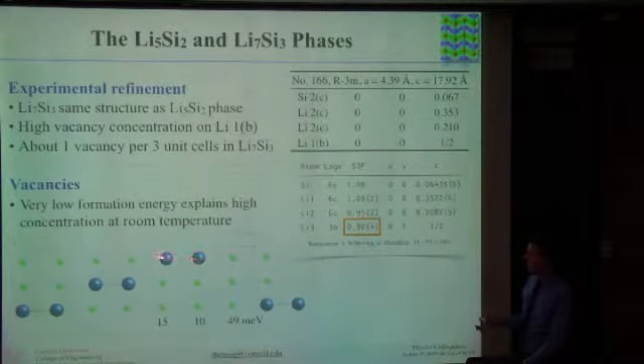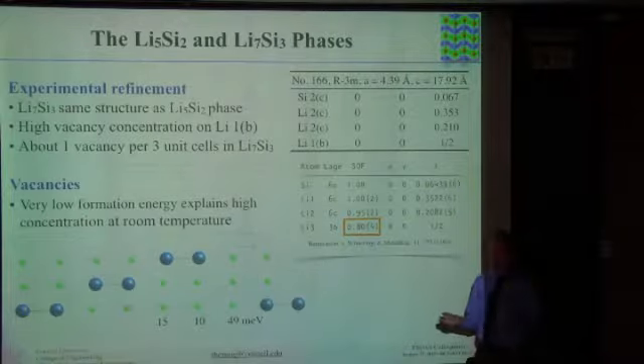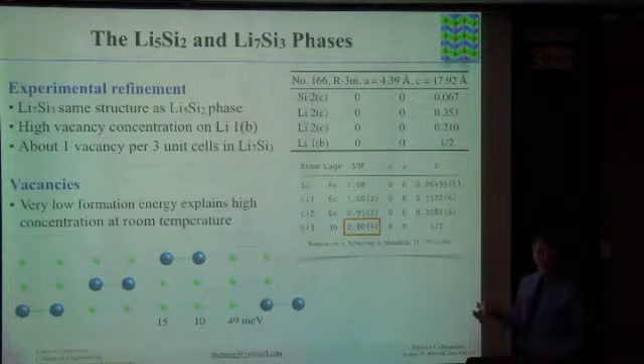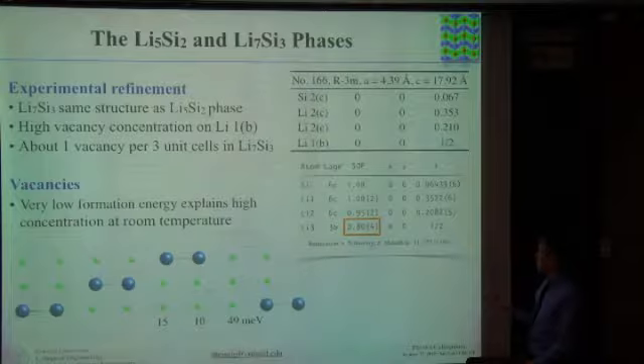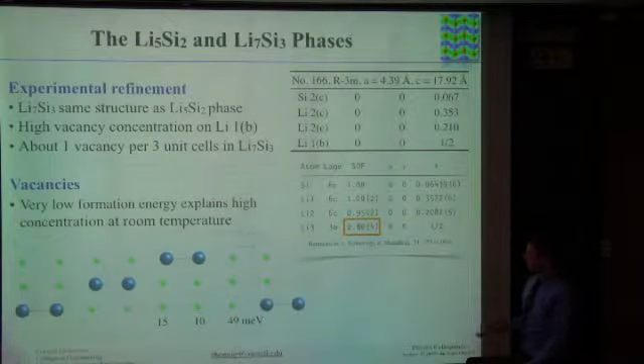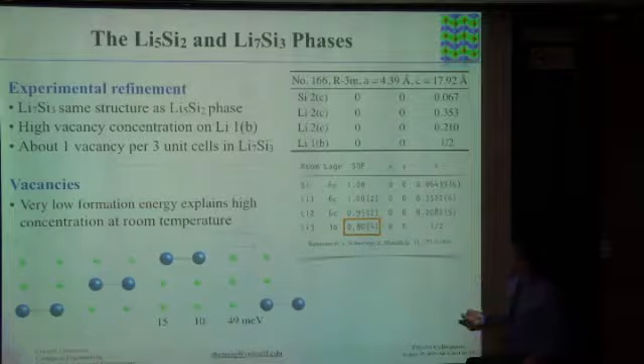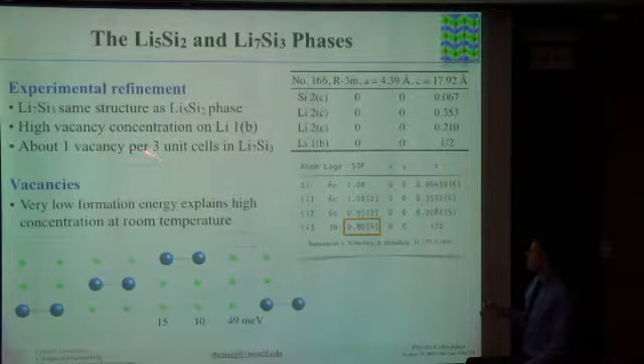So you've got little silicon dumbbells, and then here's the lithium atoms in between, rows of those atoms. And we looked at the literature for that other structure which was right next to it. And it turns out that these are pretty much the same structure. And von Schnering in 1980 actually did a nice refinement on that material. And he found that at room temperature, these lithium sites aren't fully occupied. It turns out there's a vacancy concentration of about 1 in 3. There's 1 vacancy per 3 unit cells in that structure.